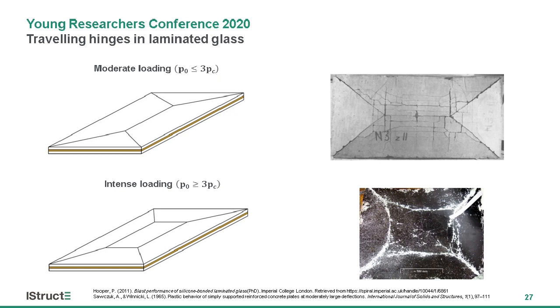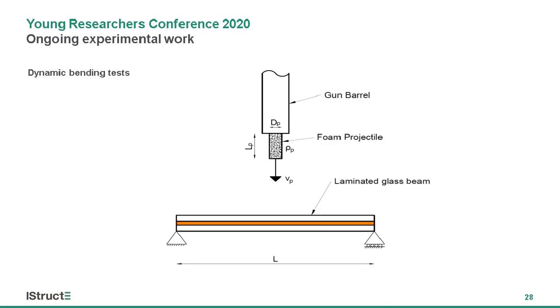To validate this theory of a yield line mechanism forming from traveling hinges in laminated glass panels, specimens will be impacted with polymer projectiles launched from a gas gun, which simulate the loading from a blast pulse. Such experimental tests have been used previously to investigate traveling hinge phenomena during the blast response of sandwich panels. The experimental work, however, is still ongoing due to COVID-19 delays.